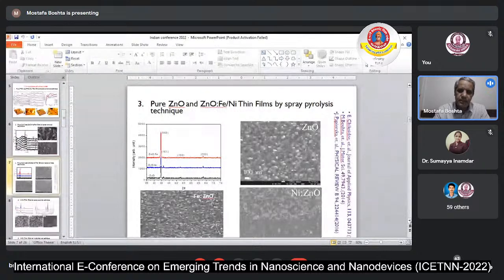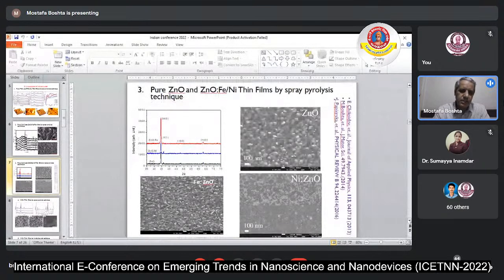After zinc oxide, we also prepared zinc oxide with some magnetic materials, like iron and nickel. We deposited pure zinc oxide, and we also have zinc oxide doped with nickel and iron by spray pyrolysis. As we see, the crystallinity and quality of the deposited material is high, not bad, very good. And we also have a good crystallinity in the zinc oxide and the zinc oxide doped with iron and nickel. The grain size is very fine and small.